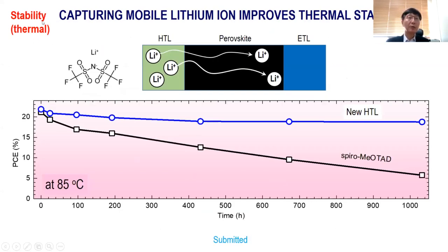And also, in terms of thermal stability, for instance, the spiro compound having an additive like LiTFSI is not good for thermal stability, because the lithium cation easily migrates to the perovskite layer, and in that case the HTL hole conductivity will be lowered. Therefore, the efficiency significantly decreases with time. So we recently developed a very good hole transporting layer which can capture mobile lithium ions. Therefore, we proved very nice thermal stability at 85 degrees C over 1,000 hours.